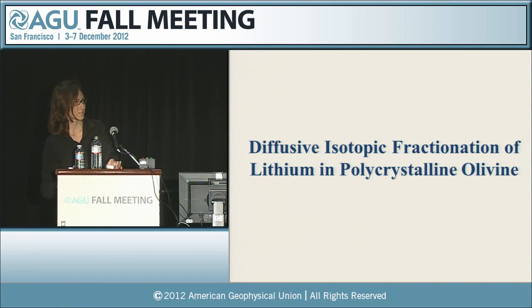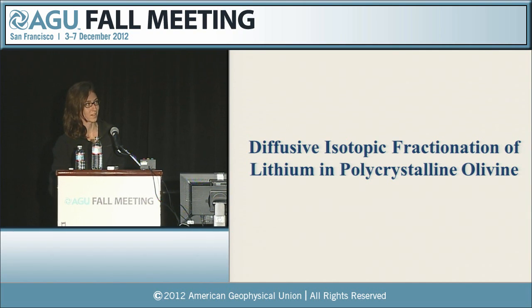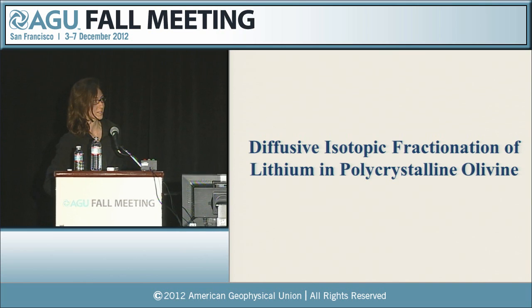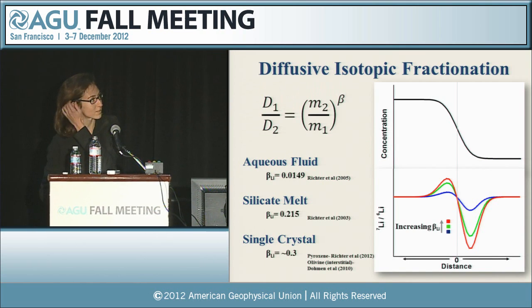So I've decided to amend my title slightly to read Diffusive Isotopic Fractionation of Lithium in Polycrystalline Olivine instead of olivine grain boundaries. So diffusive isotopic fractionation occurs because the lighter isotope usually diffuses a bit faster than the heavier isotope. The relation to describe it is seen here, where D is diffusivity, M is mass, 1 and 2 denote the two isotopes, and beta is the fractionation factor. So as the difference between the two diffusivities between the two isotopes increases, so does the beta value.